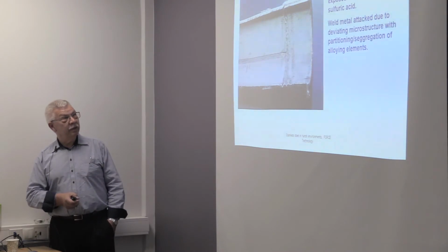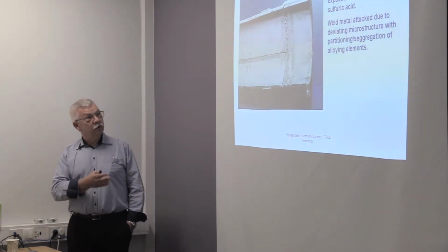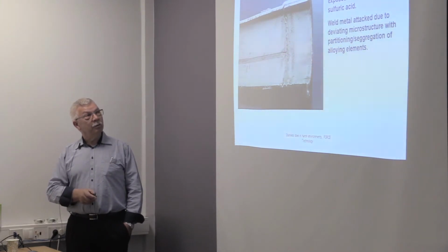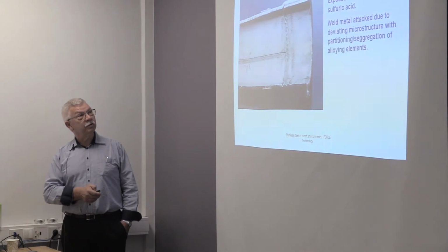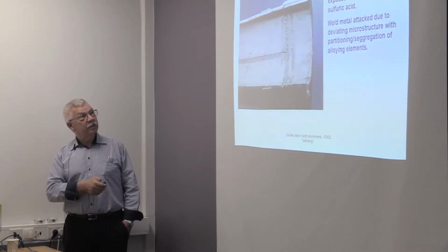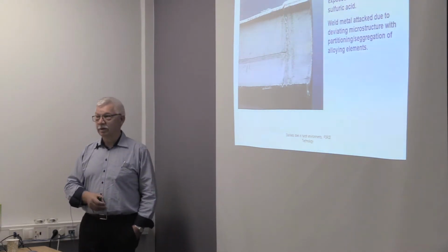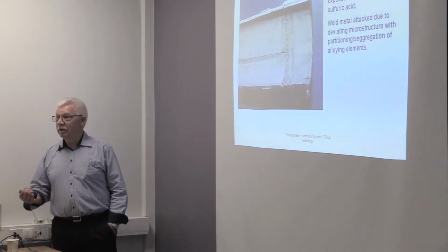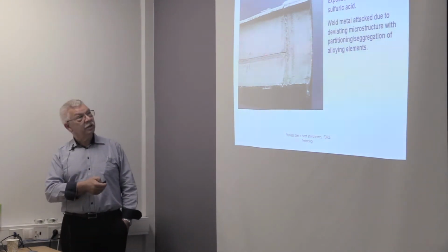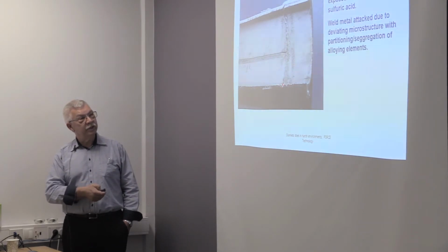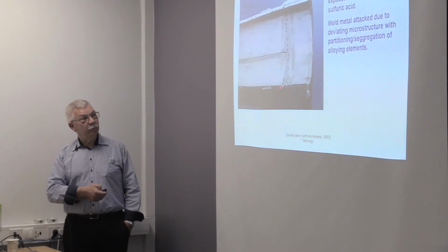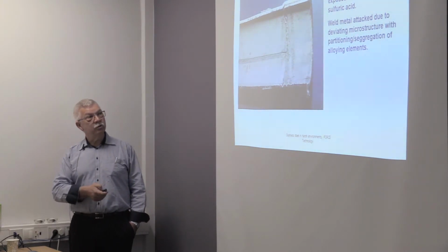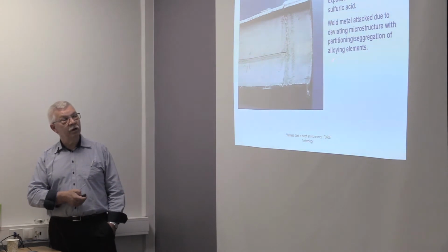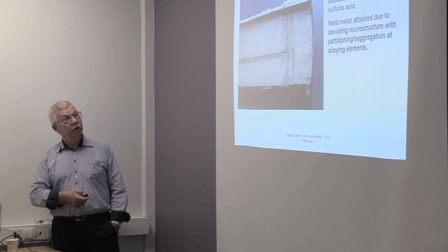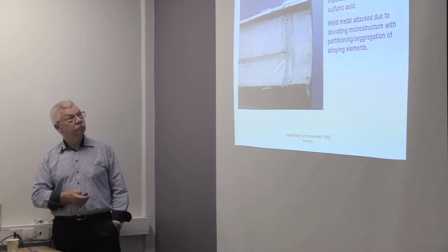And it can be seen very clearly in this piping, this tube or flange connection, which has been applied in hot, strong sulfuric acid. And as you can see, the general surface is slightly attacked, like we saw in the iso-corrosion diagrams. Something will happen, but very slowly. But the welds are clearly attacked to a much deeper level than the material. And as we can see here, at some point, we will have a leak in the weld zone. And that's due to the partitioning or the segregation of chromium and molybdenum in this structure.